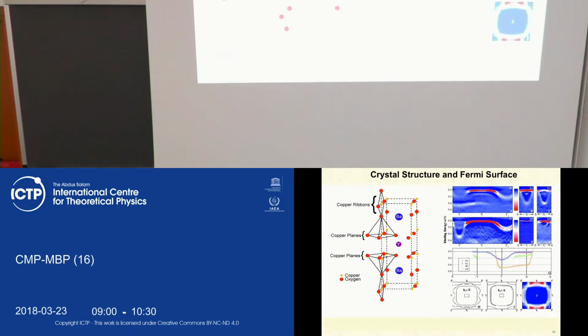The systems which I just showed you as examples are related to extra doping by oxygen. So at the stoichiometric state, these systems are insulators, as many ceramics are. Ceramics is your cup, your mug for tea or coffee, and this is ceramics. However, if you dope this ceramic, which is a very, very good insulator, and bring additional carriers to the system, it suddenly becomes a bad metal, but at the same time a good superconductor.